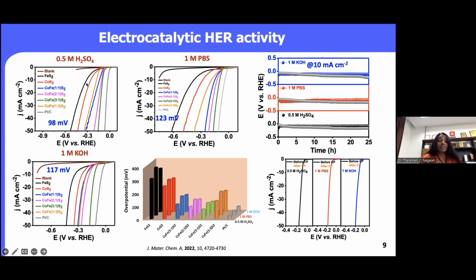However, for a single metal sulfide, the activity is quite low compared to the bimetallic sulfide materials. The same goes with the buffer solution as well. You can see that the activity is almost close to the state-of-the-art catalyst, and again with the alkaline media. This bar diagram represents the comparison across all three media.